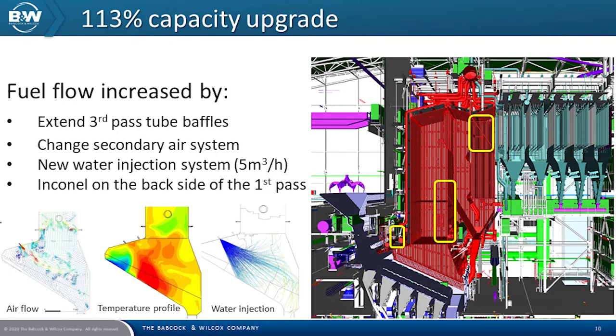On the boiler, we made several changes to handle this increased fuel flow. The tube baffles in the third pass were extended. By installing the longer baffles in the third pass, we ensured the temperature did not go too high before the convection section. The secondary air system was changed to achieve a better burnout by extending the time for particles inside the furnace. And a water injection system was installed for better combustion control overall.